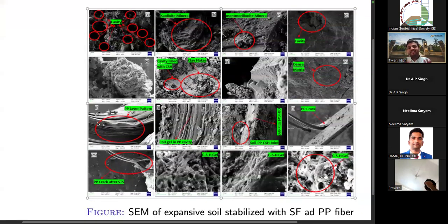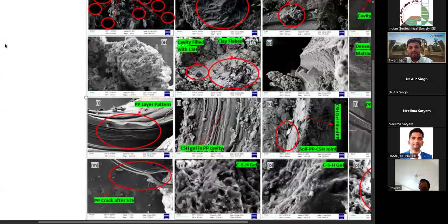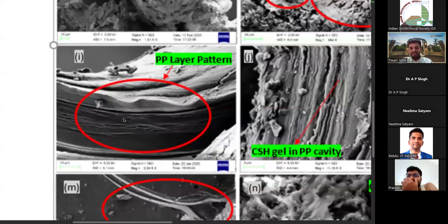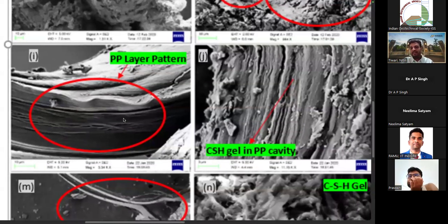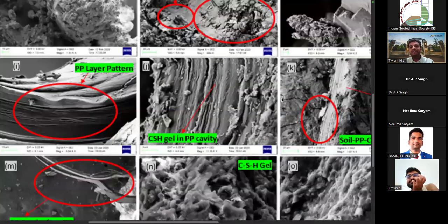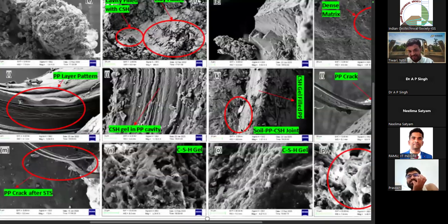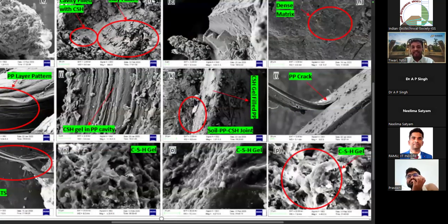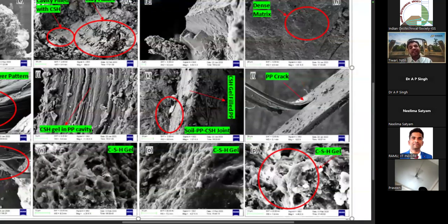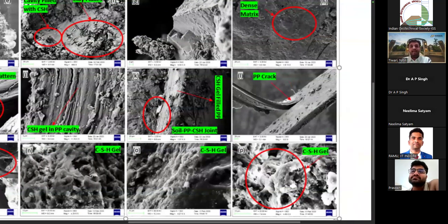We have also taken care of the fiber content. The fiber is really interesting to note. Initially the PP fiber is a layered structure. And even in these layers, the CSH gel gets filled, like you can see this kind of CSH gel, and you observe a stiff PP fiber bonded with the soil particles and CSH gel, binding together. And even when you do the split tensile test, this image is just after the split tensile test, you can see this fiber is really helping to give resistance towards the splitting.